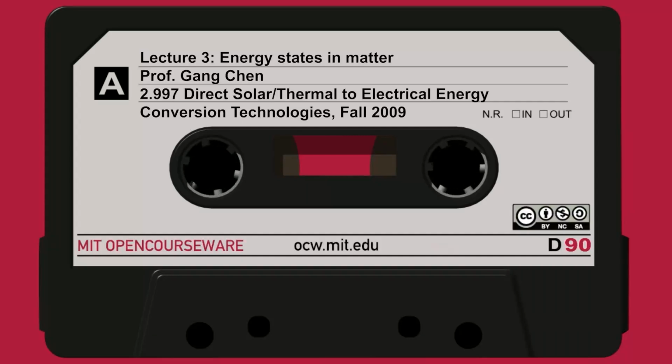Right? So basic quantum mechanics dictates the energy has to split a little bit, forming now a band. It's quasi-continuous. We plot it continuous because there are many k points. But still, between here and here, there are n points. And n is your number of atoms in the chain.